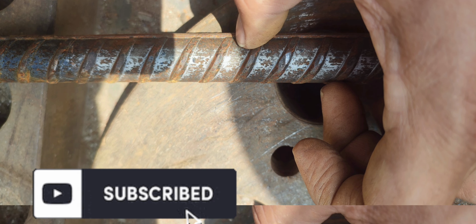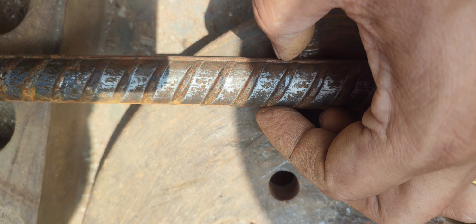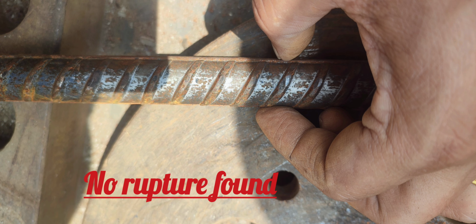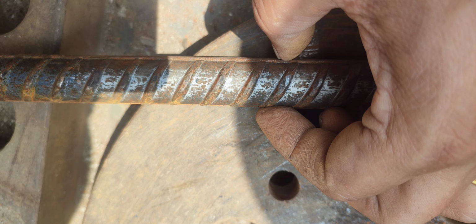Step 2. Bending. Bend the test bar through 180 degrees into a U shape using the mandrel at a uniform speed, not jerking. The test is done at room temperature. Step 3. Observation. After bending, inspect the outer tension side of the bend. There should be no visible cracks or rupture. Slight wrinkles or marks are acceptable, but cracks mean the sample fails.